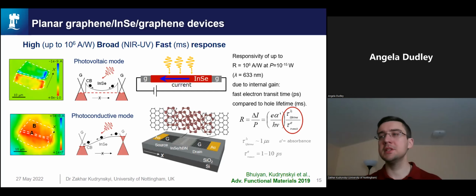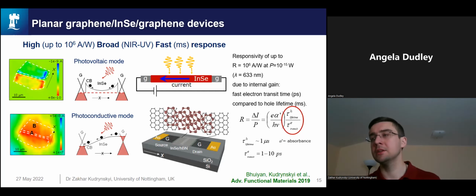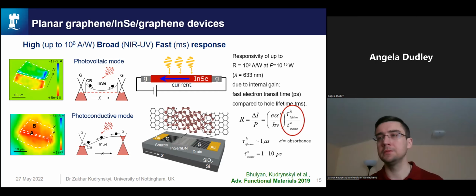The high photoresponsivity arises from the fact that the electrons can cross this gap very quickly as high mobility electrons. And the photoresponse is mainly controlled by the ratio between two times: the transit time of electrons that is short, and the lifetime of the holes that is very long.